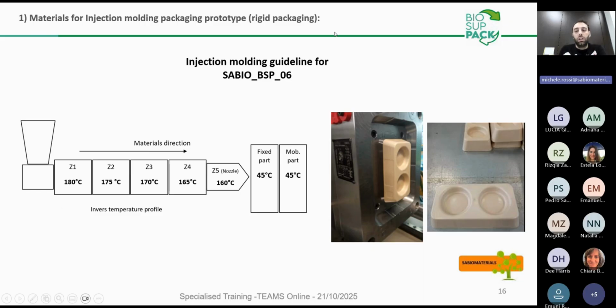temperature, but to facilitate, in this case, the injection molding and the cycle of time for the realization of one single piece, we found that it's better to start with higher temperature in the first zone, closer to the feeding zone, and decreasing the temperature along the screw of the injection molding. This is a typical inverse temperature profile, keeping the material inside of the mold at temperature of 45 degrees to facilitate the crystallization of the material.